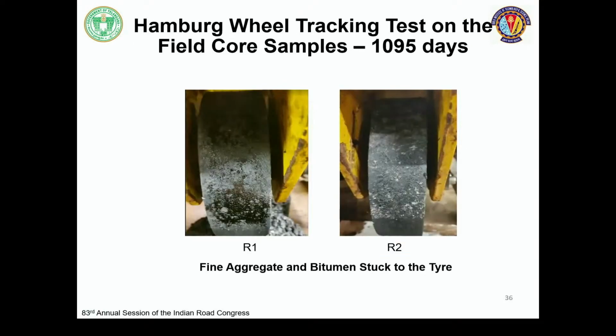Yeah. So we tried to cut the core and did a Hamburg wheel tracking study. Why did we do this? I spoke about traveling. Will the rubber tire remove the aggregates? To our surprise, the fine aggregate was removed from road number 2, where the air voids were quite high. That was because the fine aggregate coated with bitumen was getting aged and drying up. When the rubber wheel moves on that, it was just removing it from the surface.